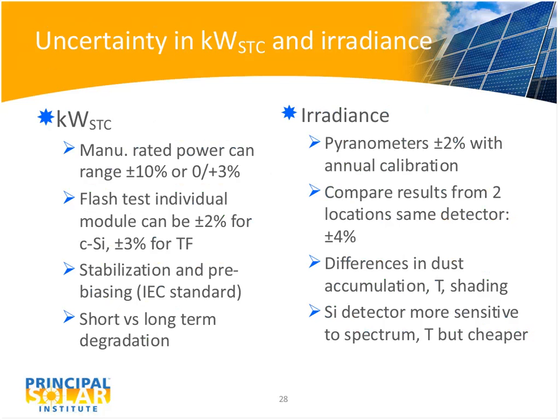So there's a lot of uncertainty, though, in these numbers. If we're going to say that that 5% number that I just calculated is meaningful, that assumes that we can determine the initial performance and the measured kilowatt-hour performance to better than that sort of number. So when you look at the kilowatts rated power, there's quite a wide range of powers, and so typically a module manufacturer might sell modules at 240, 260, 280 watts, or maybe 280, 290, 300. But they're going to bin them, and there's going to be a range. So if you buy a 250 watt module, it could be between 245 and 255. Okay, so that's like plus or minus 3% variation.